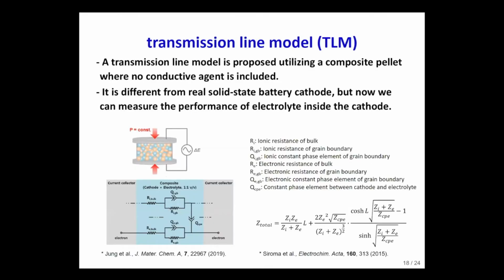As an indirect method, we adopted a transmission line model to describe the composite cathode. There are two parallel transmission lines in this model. One represents the electronic conduction, and the other represents the ionic conduction. The electronic conduction is non-blocking, but the ionic conduction is blocking. A mathematical model is well established for this case.